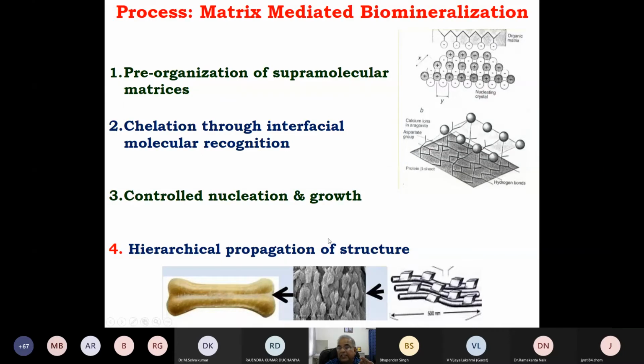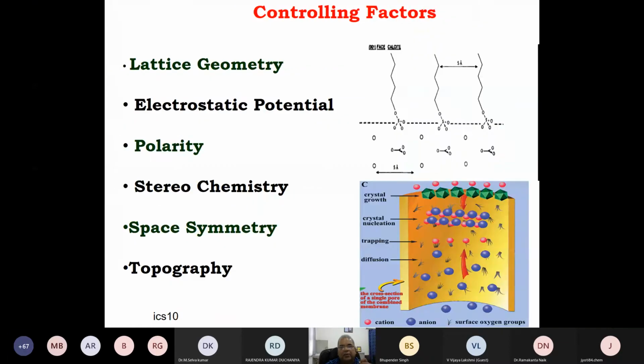So once the nucleation has taken place and some growth has started, the system will try to minimize its free energy. And to reduce the free energy, it is nature's intelligence, the system will self-assemble itself in a particular shape and size depending upon the conditions present over there. And in this way, our bone formation takes place. This is the entire process of biomineralization. Though it looks very simple, that you take any supramolecular matrix and put cations or anions into it, then expose to the subsequent ion, and you will get controlled nucleation and growth, no, it does not happen so easily.